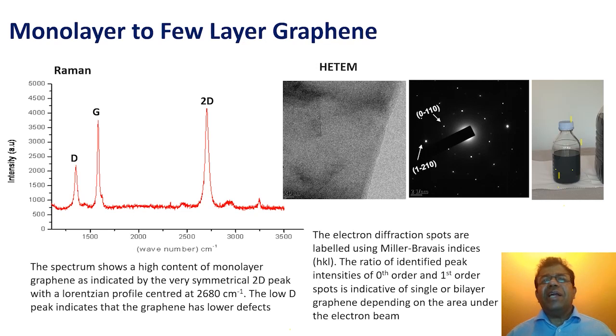In HRTEM, the electron diffraction spots are labeled using Miller-Bravais indices. The ratio of the peak intensity of the zeroth-order and first-order spots is indicative of a single layer or bilayer of graphene in the area under the electron beam.